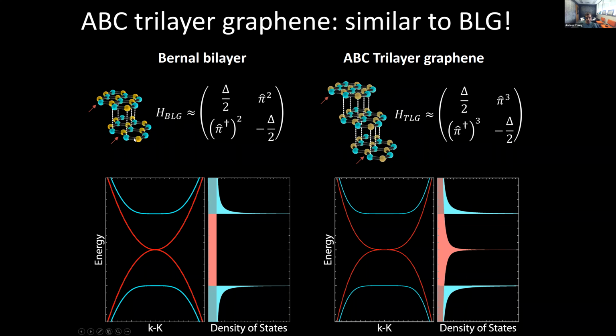The idea here is that as you build up stacks of graphite, but not conventional graphite, rhombohedral graphite. So in normal graphite, you have Bernal stacking, which means that you have essentially three choices when you stack two layers on top of each other. You could actually stack them exactly the same, right, with each atom on top of each other.